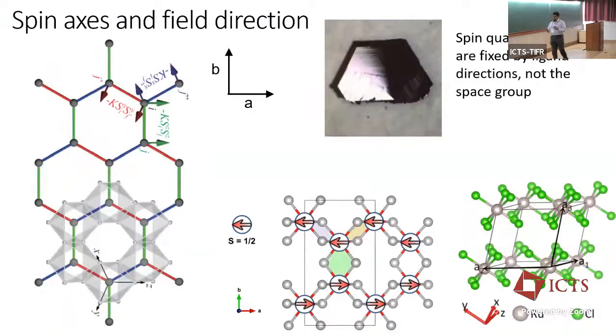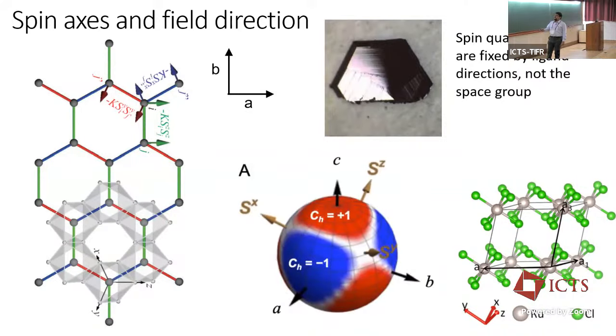One thing that I want to tell you before I get to the next point is that the spin quantization axis of this material is very important, and that was one of the mistakes which the community was making. Essentially, the spin quantization axes are fixed by the ligand direction. The spin quantization axis is along the ruthenium-chlorine ligand bonds, and they come out of plane. So there is a translation between the spin quantization axis, or the Ising axis, and the space group. The space group does not define the spin quantization axis in the system. That will become very important very soon, because that was what was used by Yokoi et al. in their Science paper to figure out which direction you would have a Chern number of plus one and which direction you might get a Chern number of minus one.